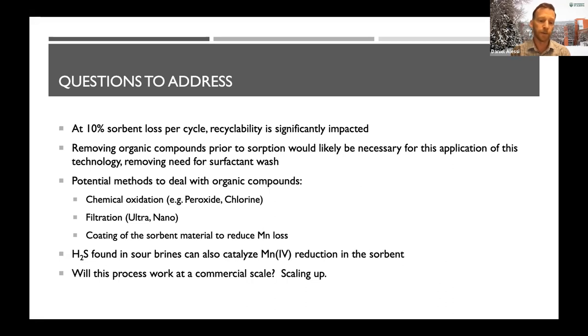And the other approach that we're working on now, both with E3 Metals, with whom we have a collaboration down in Calgary, and also through the Future Energy Systems Program here at Alberta, is coating the sorbent itself. So again, we have these nanoparticles that are made of manganese. What we can do is put a thin micron or nanometer scale veneer of another material on the surface. We're working on zirconium, it turns out. This material ends up being porous enough to still let lithium and protons in, but it would protect the outside of the mineral from the reductive dissolution, right?